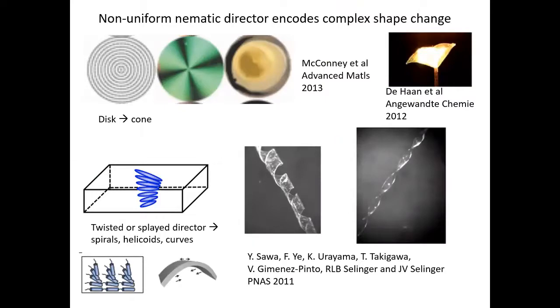Now the thing is, if the nematic director is uniform, then all you have is a material that just gets longer and shorter, like the picture I showed with the temperature. It's just simple. What if the nematic director goes around in a circle, for instance? So here's a case where the nematic director goes around in a circle. If you look at this through polarizers, where the nematic director is parallel to the polarizer or the analyzer you would see dark, and otherwise you would see light. So you can see that there's really a bullseye picture here. When you heat this up, you get something that looks like a mountain or a volcano.